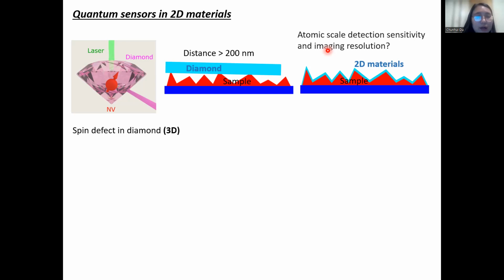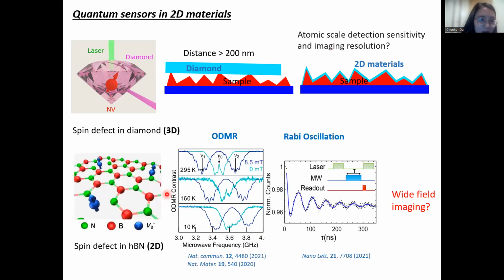So thanks for the pioneer work. The answer is yes. So people find that spin defects in hexagonal boron nitride, for instance, boron vacancy centers, show very similar properties as NV center. So the boron vacancy center was first discovered in 2020. And people have shown that it shows very clear optically detected magnetic resonance. And we can use that to measure the external magnetic field, electric field, temperature, pressure, and also microwave field and the dynamic field environment.